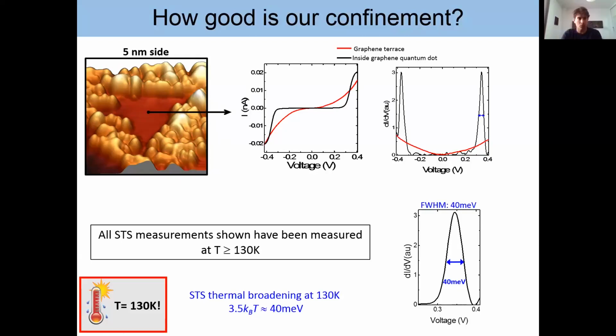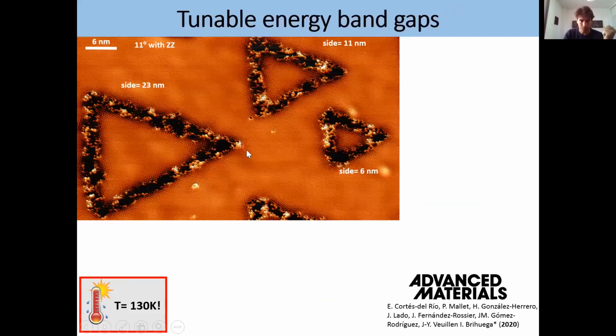Eva worked very hard to do this, and that's what we get. And we get a broadening of around 40 millielectron volts. And this broadening is essentially the same broadening that you get due to thermal effects. So the only thing that we can say is that our confinement is very good. So it's on our energy resolution. We cannot resolve really how sharp it is, but it appears to be very sharp. So we can say that our barriers confine very well massless quasiparticles.